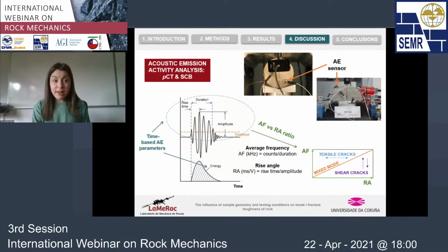We have also recorded acoustic emission activity using these sensors here on the surface of the sample. We have recorded many time-based acoustic emission parameters, the most typical ones: amplitude, duration, the energy. And we have also computed a couple of ratios, which are called the average frequency and the rise angle, using these parameters. If we plot these magnitudes on a graph, we can assess if the acoustic events are being produced by tensile cracks, by shear cracks, or if there are mixed mode conditions.